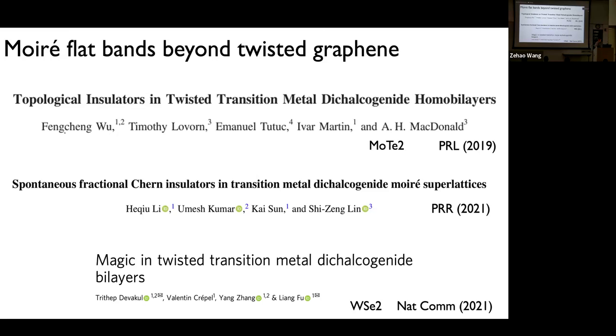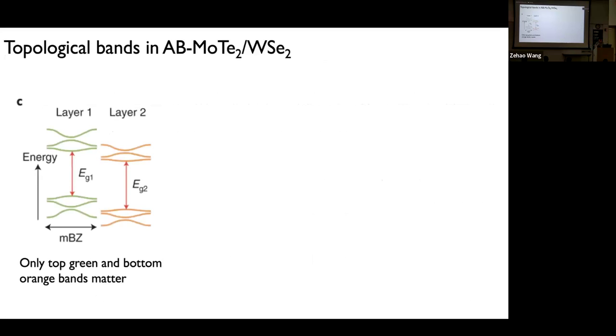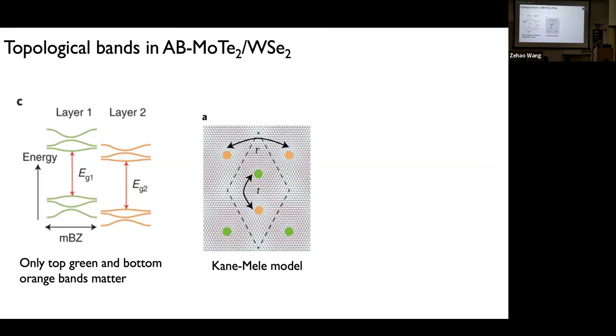So people have been trying, already after the first prediction back in 2019. The first material system that people tried is to take MoTe2 with WSe2. There's some reason about band alignment, etc. And then, as mentioned yesterday, the two layers have their own bands, but they are pretty strongly localized. And in fact, what matters is, for example in this case, only the top green band and the bottom orange band. And for those who are familiar, people argue that this kind of material system realizes what's called a Kane-Mele model.